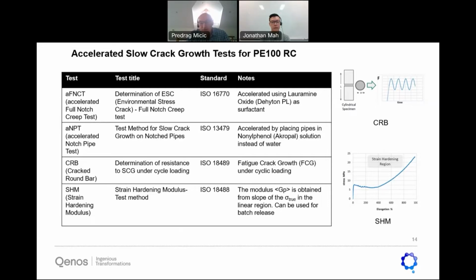But there are 2 new tests. One is the cracked round bar test, which is the determination of resistance to slow crack growth under cyclic loading, and you can see it in the top right schematic. We introduced the cyclic loading. It's done at room temperature. So this is what I mentioned, that there are tests now introducing different strain and stress conditions that we may encounter in the field, and they can lead to slow crack growth, not just a static pressure. The big accelerant is also fatigue, the cyclic strain.